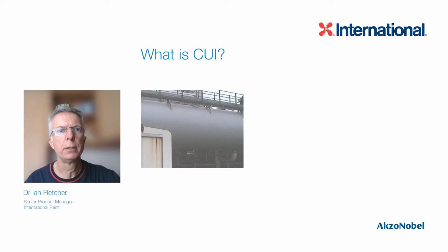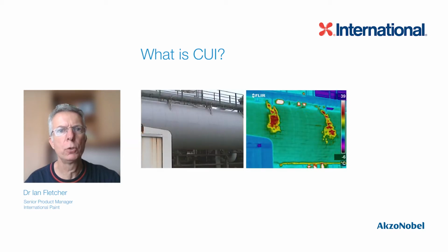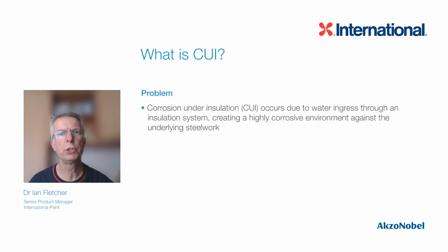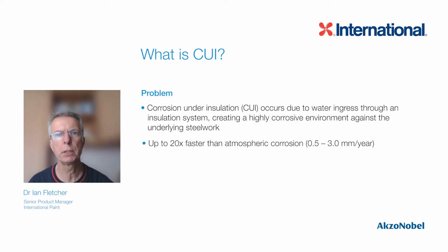So what is CUI? Corrosion under insulation, or CUI, is the silent killer that you can't see, and if left unchecked, will lead to a serious problem. CUI occurs due to water ingress through an insulation system, creating a highly corrosive environment against the underlying steelwork. And CUI's corrosion rate can be up to 20 times faster than atmospheric corrosion, resulting in steel loss of between 0.5 and 3 millimeters per year.